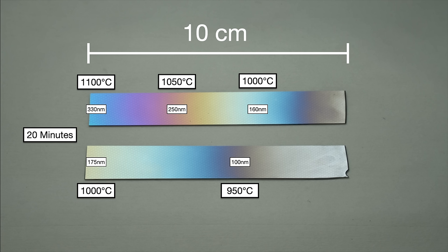That isn't horrible, but in the future I'm going to plug the ends of the tube, and I'll probably also make the tube longer to mitigate this problem. I'm also going to use pieces of silicon that are much smaller than this, so the uneven temperature should be less of a concern then. In larger tube furnaces you can load the wafer in vertically, which mitigates this problem somewhat.